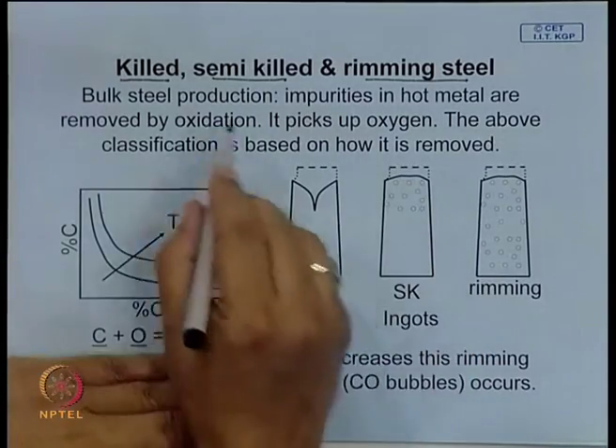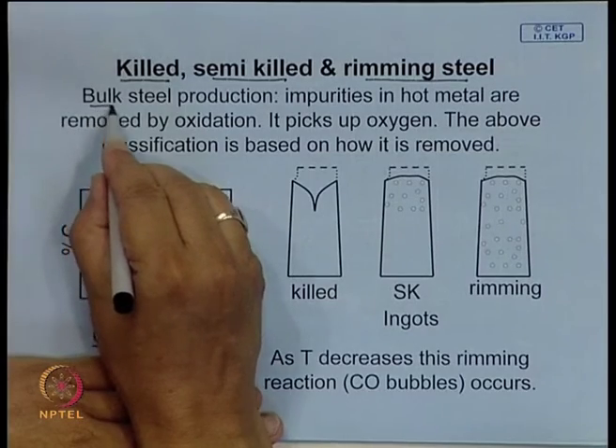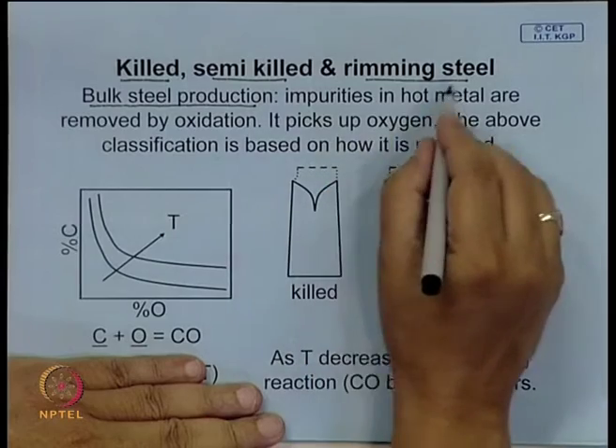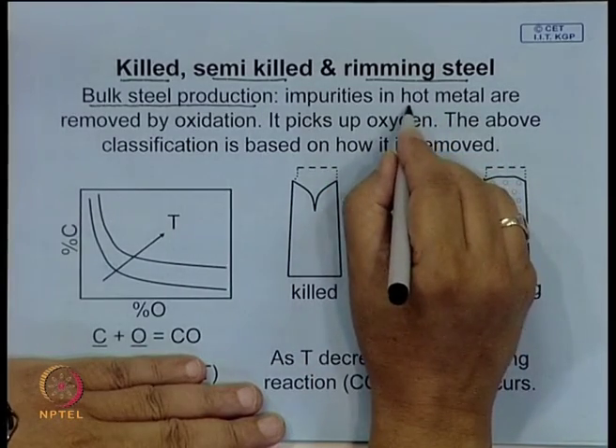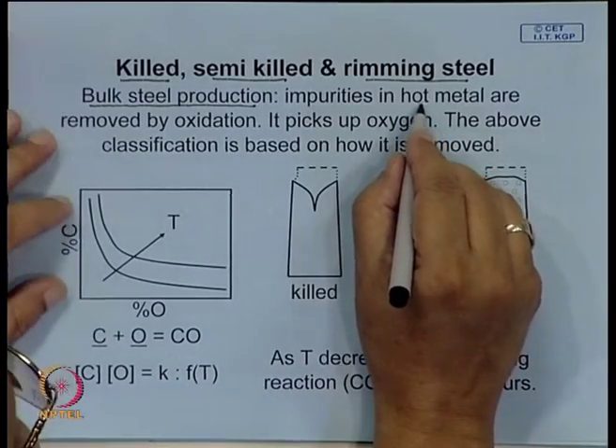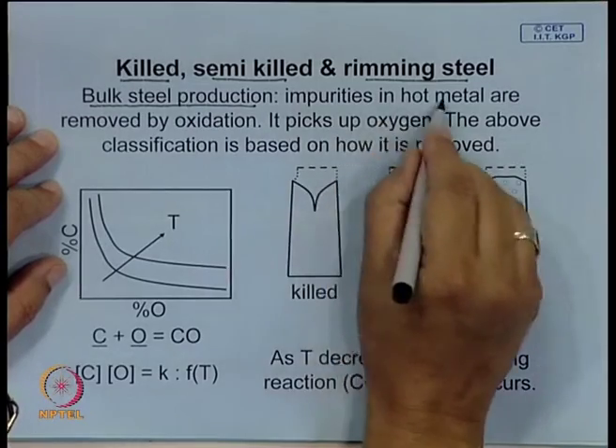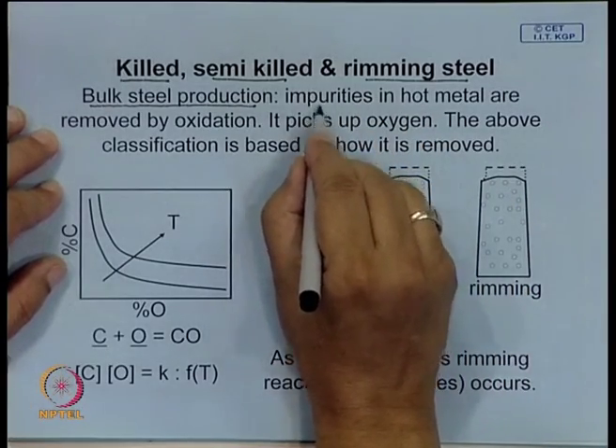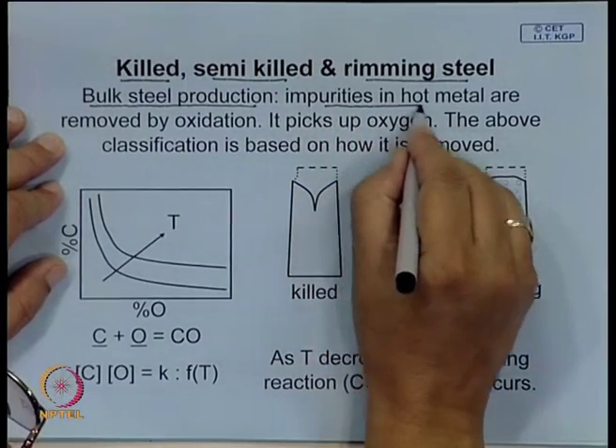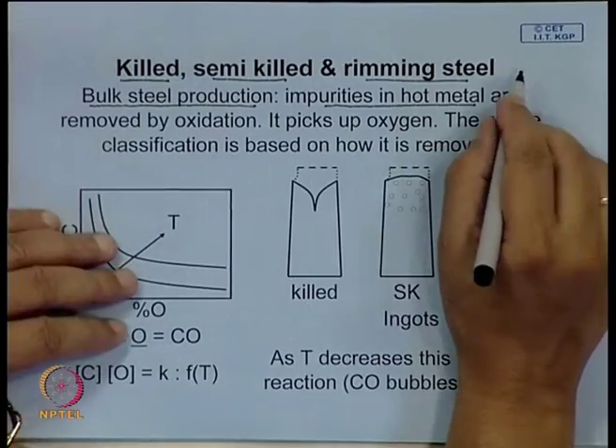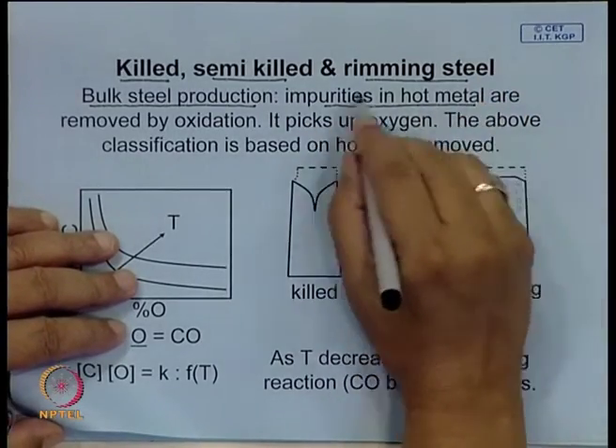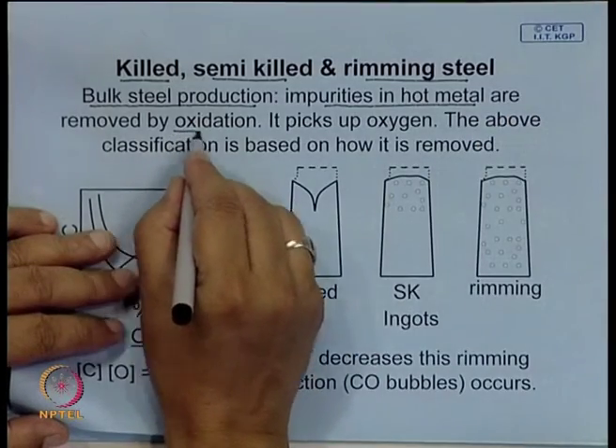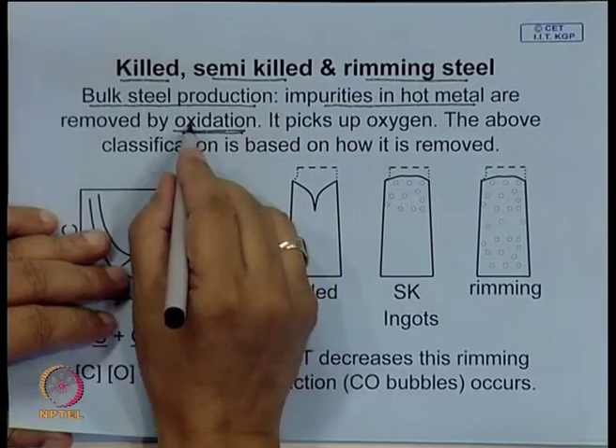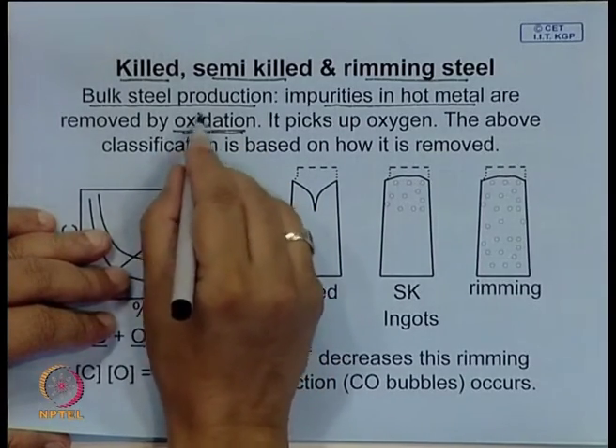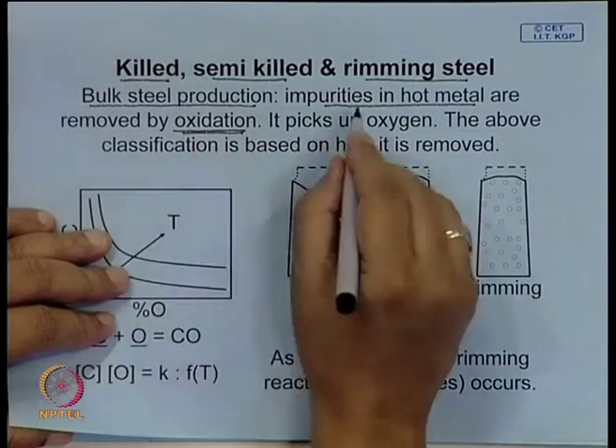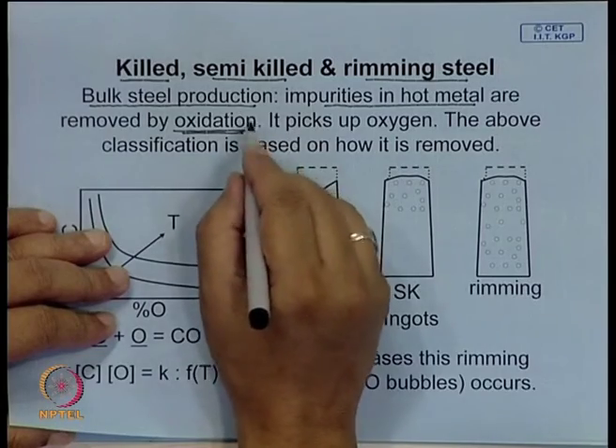If you look at the bulk steel production technique, it is produced from hot metal, which comes from, let us say, blast furnace hot metal, which is actually a cast iron. It has a very high carbon content, maybe around 4%, it has silicon also, and it also has sulfur and phosphorus, and they must be removed to make it steel, because such high carbon material is extremely brittle, and cannot be formed. So these impurities are to be removed, and this removal is done by an oxidation process. So in the basic oxygen furnace, BOF, oxygen is blown from the top, and this oxygen reacts with these impurities, and these impurities are absorbed in slag.